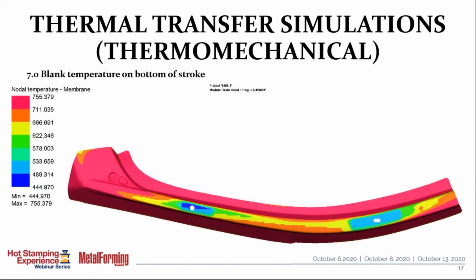So earlier I mentioned thermomechanical simulation. Basically, we're forming and extracting heat. We're also generating heat because as we form, we generate heat. And so we have to evaluate that. So a good thermomechanical simulation tool will be capable of doing that.